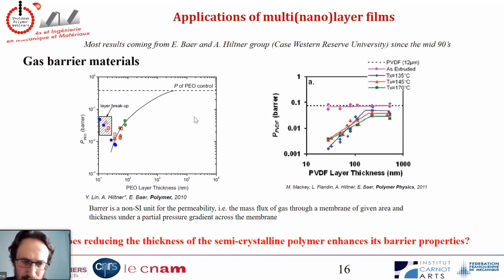you can improve it. So this is the barrier property, or the permeability, of the PEO polymer. The lower it gets, the better it is for the barrier, as a function of the layer thickness of the PEO layers. If I go from micron scale to nanoscale, the bulk permeability of PEO is there, and the confined PEO permeability is there. So I can lower my permeability by almost 2 orders of magnitude by going from micron thick layers to 50 nanometer thick layers. This result has also been observed for other polymers.